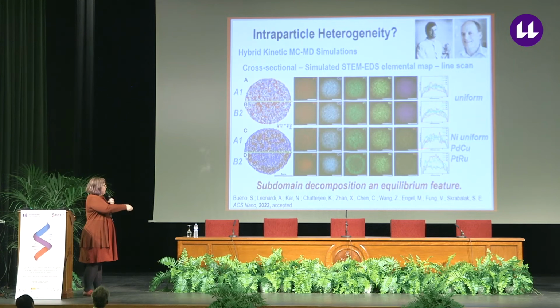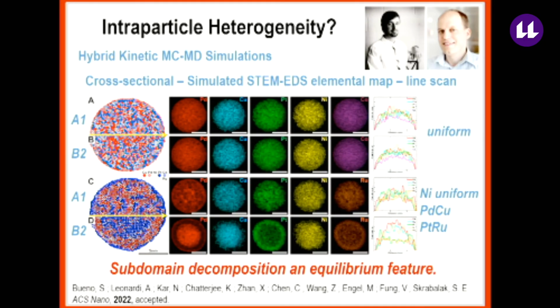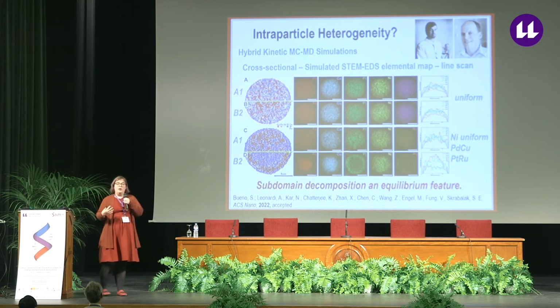But I got really fascinated about this result here on the top, where in the cross-sectional view, we see these islands of different enrichments. But if you look in the simulated STEM EDS elemental map, the metals appear to be fully mixed. And that's because STEM EDS is showing a 2D projection of a 3D distribution. And so I'm anticipating that there may be many examples in the literature where people have made an assumption that they have atomic level mixing of all of these components, but the reality is that there are some segregated domains that you just can't probe because of it being this 2D projection of that 3D distribution.